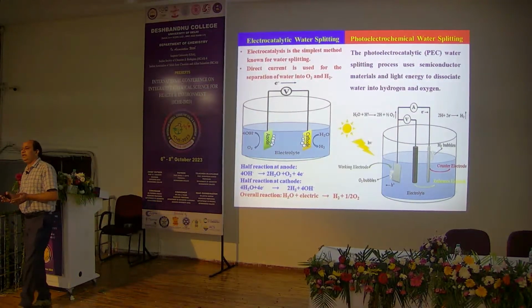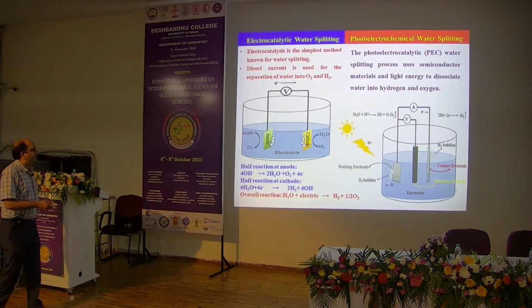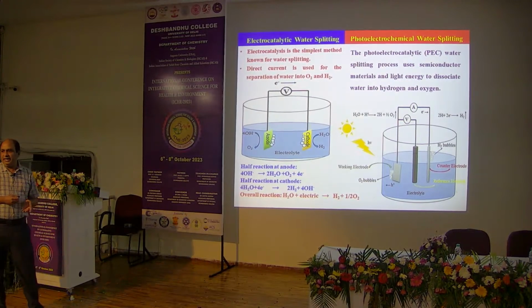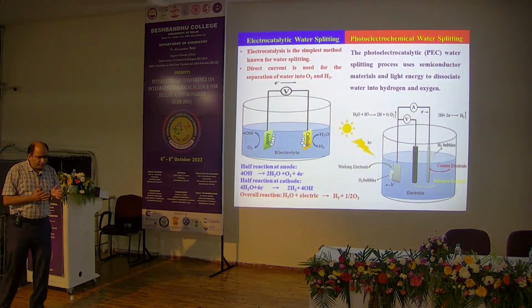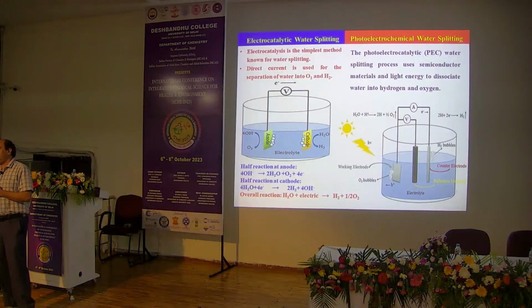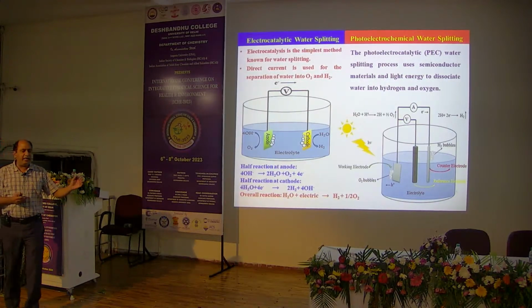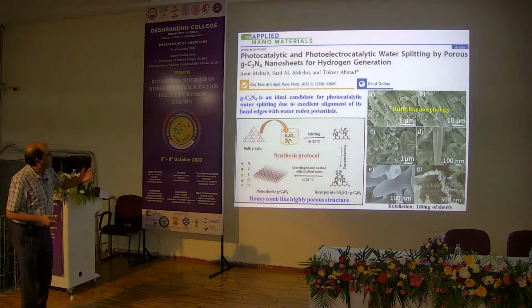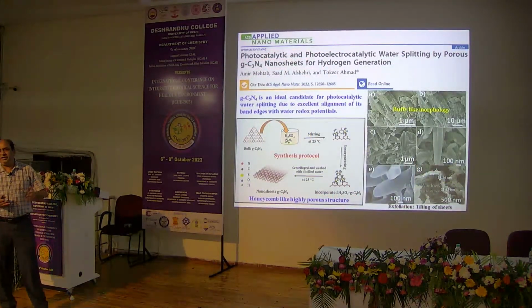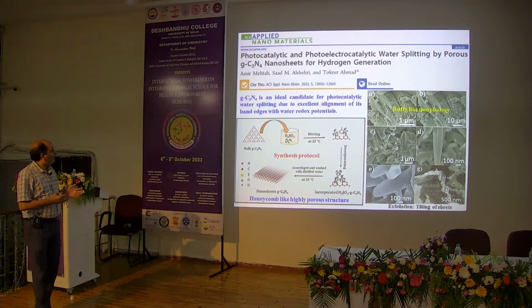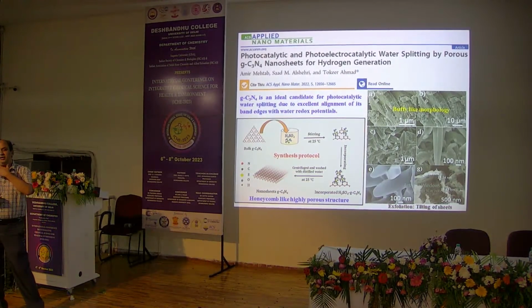The difference is that in one set of reactions we use the light source, and the cell setup is different because you need to make an arrangement so that you can easily pass the light in this setup. So first we have prepared this material, the graphitic carbon nitride nanosheets, because we took graphitic carbon nitride for making the different heterostructures.